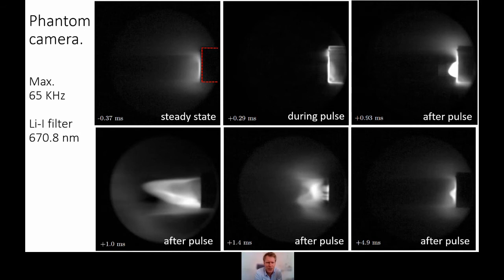from left to right and from top to bottom, what's happening in chronological order. You see in steady state the target outline in red, and there's a white lithium cloud. That's because it's just a black and white image that is right in front of the target. And then during a pulse, suddenly we get this bright layer of light wrapped around the target. And you can see after the pulse that this layer expands rapidly. It expands really fast. So it appeared that there was, in fact, some sort of compressed high-density vapor layer,